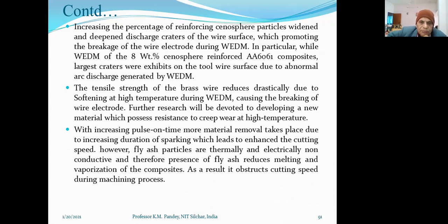Then, with increasing pulse on time, more material removal takes place due to increasing duration of sparking, which leads to enhanced cutting speed. However, fly ash particles are thermally and electrically non-conductive, and therefore presence of fly ash reduces melting and vaporization of the composites. As a result, it obstructs cutting speed during machining process.